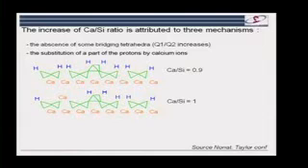After a certain point, we can't go any further by just removing these bridging sites, and then we can continue to change the calcium-silicon ratio by replacing 2 hydrogens with 1 calcium. This is the next stage to increase the calcium-silicon ratio, and in this way we can go to a ratio of about 1.2 or 1.3. And then the question is, we're still below the calcium-silicon ratio of CSH. How can we get further?